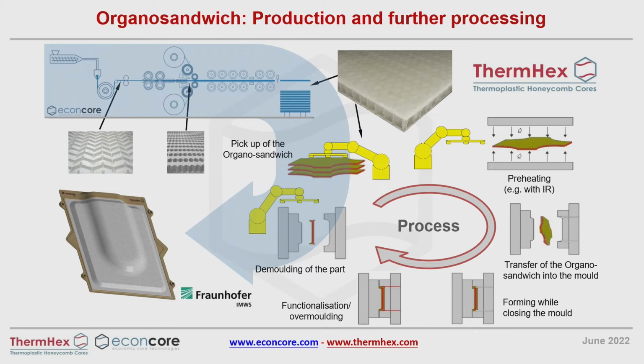So for the luggage floor especially, or for automotive in general, the Organosandwich material is a material where we directly inline join UD cross-ply skins on our core. So we produce the core and directly have UD fiber reinforced skins on the core. And this material can then be further processed with injection molding or compression molding equipment by preheating and then very fast forming and finishing of the part, optional with injection overmolding.